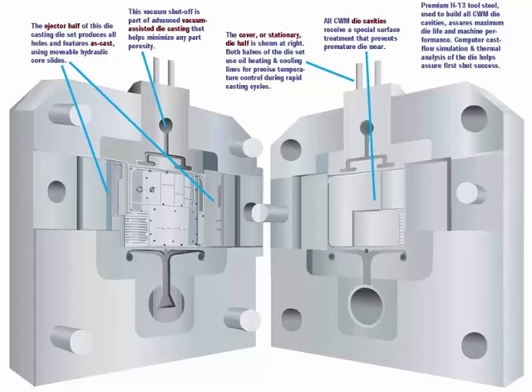Here is a blow-up of the die that we were showing a minute ago, just to show some of the features. You can see at the bottom here where the metal flows into the part. It then flows across the part, and then out here. There's some overflows on this area, and then the runner system goes out to a vacuum assist system. So we're forcing in the metal at very high pressures. We're pulling at the other end with vacuum to try to get as much air out as possible. Internal porosity is obviously a big thing that is desired to be controlled, so we do whatever we can to do that.